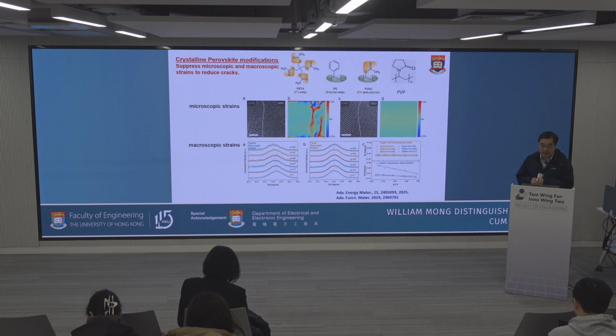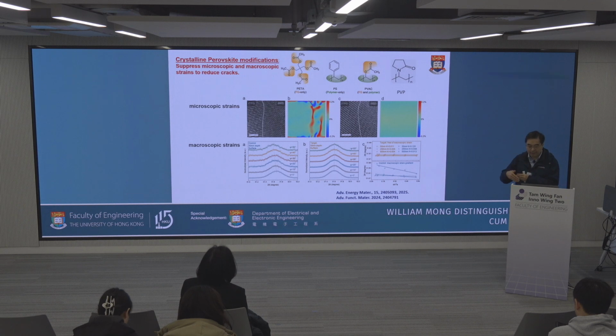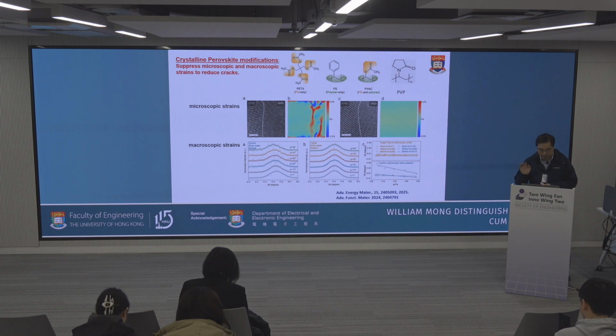One is the delamination. My team member already studied a new kind of material that has a strong interaction between the underneath structure and the perovskite, helping to suppress the delamination of the layers. Because the PV device typically has multiple layers, it depends on what type of structure. If it starts from anode, hole transporting layer, perovskite, electron transporting layer, and then cathode, that is a basic PIN structure, right? So each layer is a different material. When you bend them, there is delamination. But I haven't shown you the slide there. Here, we address this by a new small molecule that can help to have a stronger bonding between the different layers, suppressing the delamination.